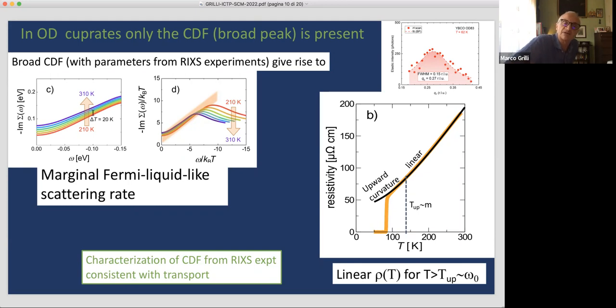And you do find that the self-energy for the itinerant fermions dressed by these charge density fluctuations has exactly the marginal Fermi liquid-like form. So all the properties of the marginal Fermi liquid as a phenomenological theory can be reproduced thanks to this microscopic charge density fluctuation mechanism. What is interesting in transport is also that these charge density fluctuations have a characteristic energy, omega naught, of order 100, 120 Kelvin, so 10 millielectronvolts. And precisely at this energy, which is found with RIXS experiment, we do find deviation from the linearity. So transport experiments and RIXS experiments are consistent even in the deviation from the linearity.